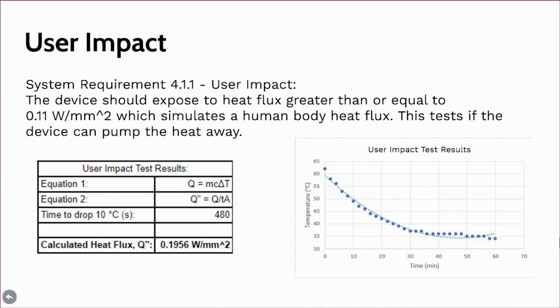The heat transfer equation 1 and heat flux equation 2 were used with the data obtained from the test to find the heat flux of the device. This was calculated to be 0.19 watts per millimeter squared, which meets the requirement.